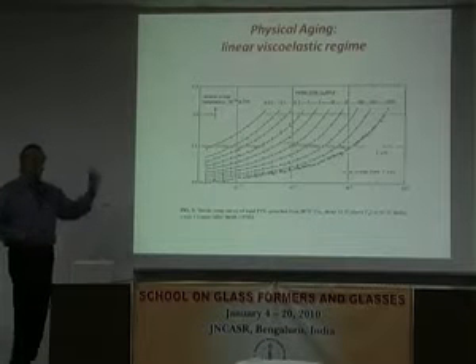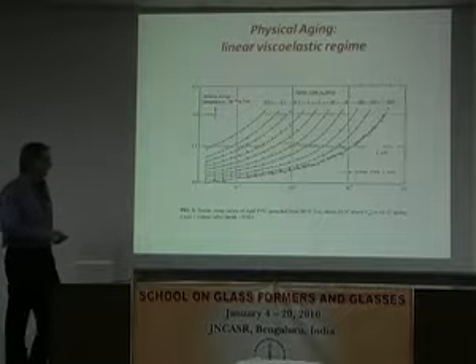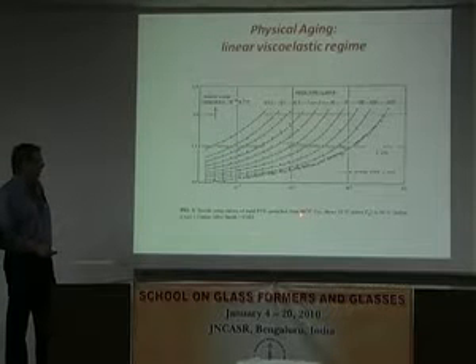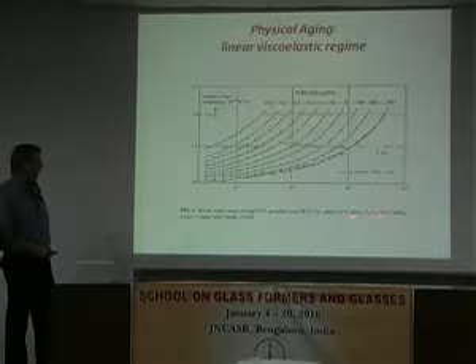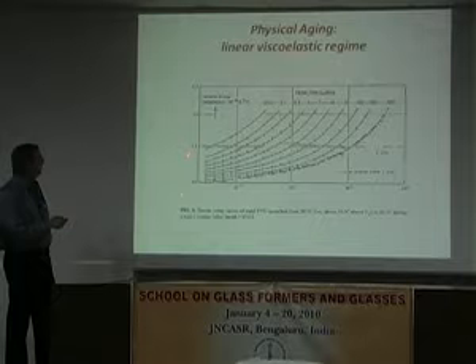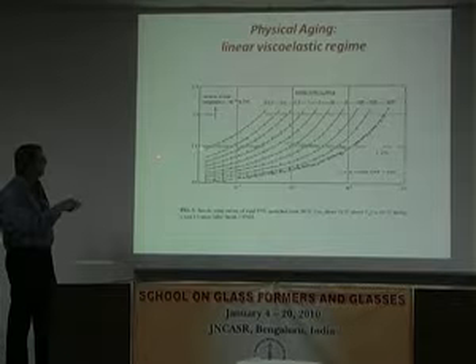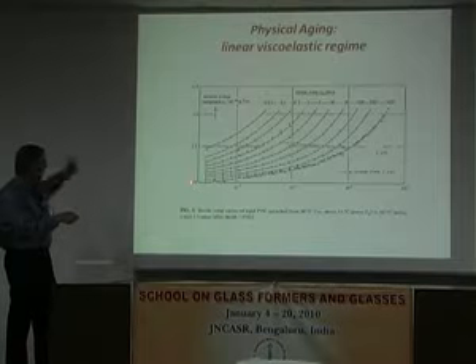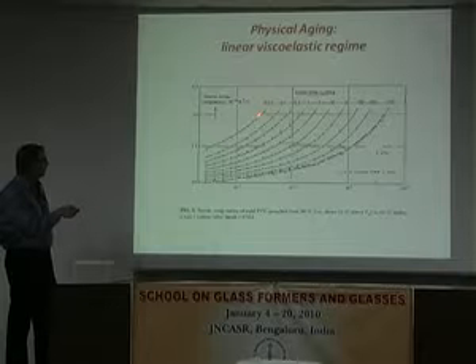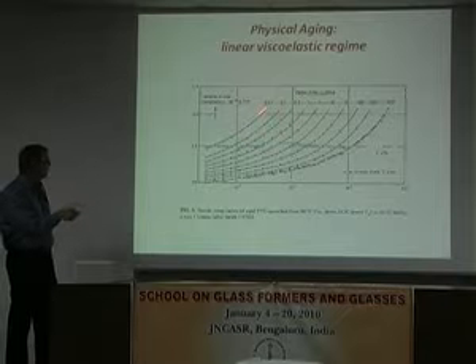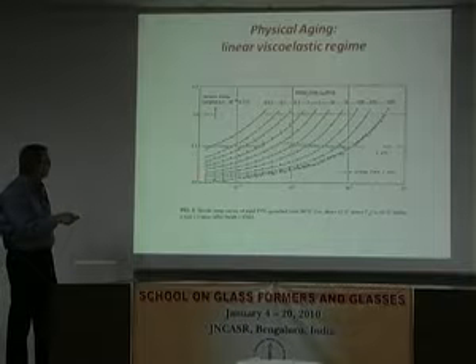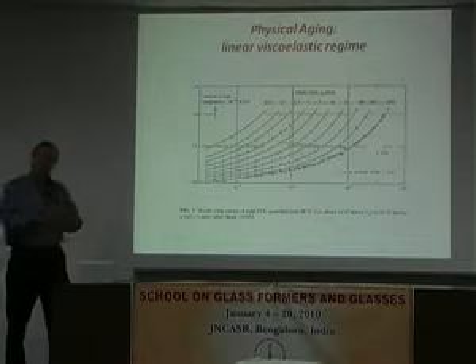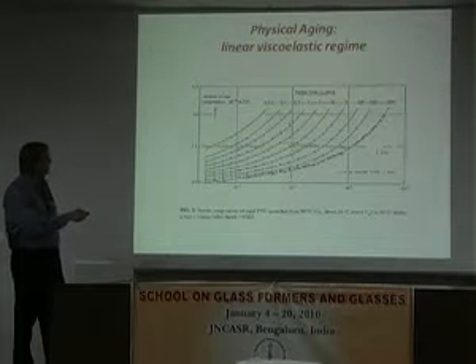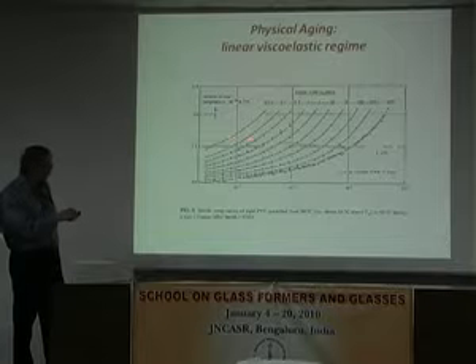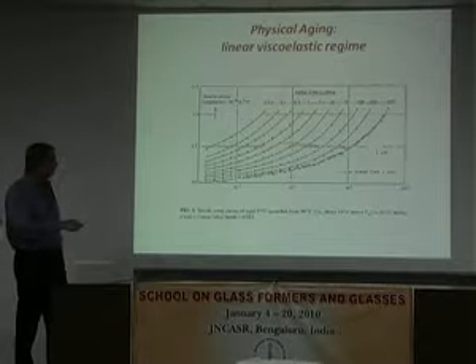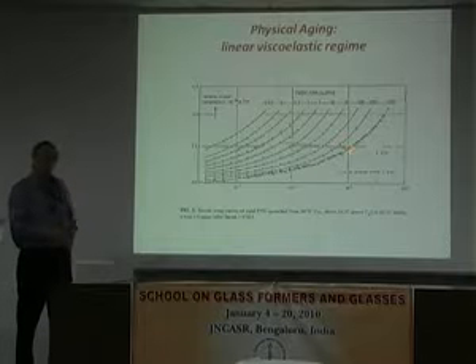So then when you do that, here's the response. This is a polyvinyl chloride glass that was quenched from about 10 degrees above the glass transition to about 40 degrees below the glass transition. And what you see is the creep response. Load is applied to the sample, and this is the strain divided by the load. And you can see that as we go to longer and longer aging times, these curves shift, so the material is getting stiffer. The other thing that Struik found was that he can essentially perform aging time superposition to create a master curve with small vertical shifts.